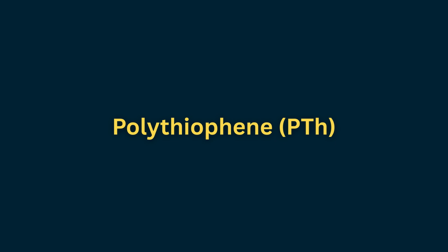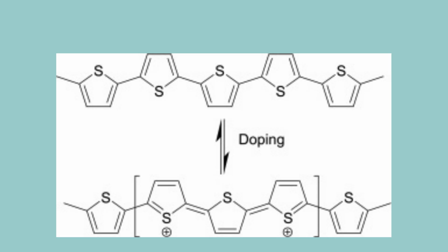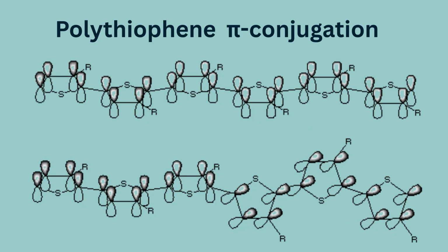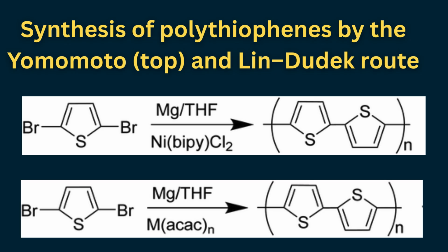Polythiophene, PTH. Polythiophene exhibits stable and tunable conductivity depending on dopant type and polymerization conditions. Conductivity correlates with conjugation length. Oligomers containing approximately 11 thiophene units show conductivity comparable to high molecular weight PTH. Because conjugated polymers are typically non-transparent, transparency can be improved by dilution strategies such as block copolymerization, alkyl side chain grafting, blending with transparent polymers, or forming composites within insulating matrices.